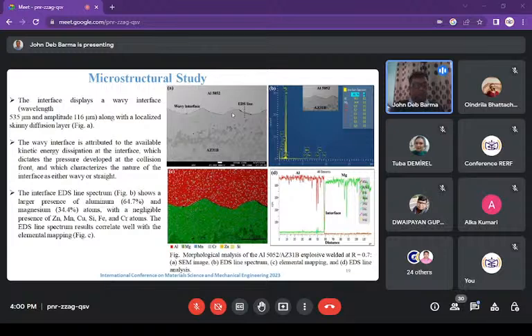And the wavy interface formation, whatever we can see, is very much attributed to the kinetic energy that was dissipated at the interface. And that kinetic energy dictated the pressure that was developed at the collision front. And that ultimately characterized the nature of the interface as either wavy or straight. So as we are getting wavy, this wavy also is due to the dissipation of the kinetic energy. We may get straight also. That also depends on how much kinetic energy is dissipated.